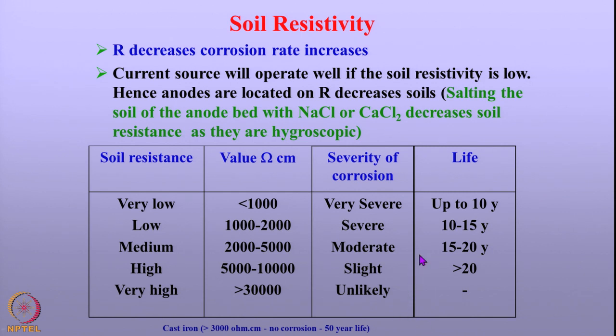This table gives you some kind of comparison between the soil resistivity and the extent of corrosion a steel pipeline may suffer. As you notice, when the soil resistance is lower than 1000 ohm centimeter, the soil has very high severity in terms of corrosion. As the resistivity of the soil increases, the severity of corrosion decreases. In fact, if the soil has a resistivity greater than 30,000 ohm centimeter, it is very unlikely that the pipeline will suffer corrosion.